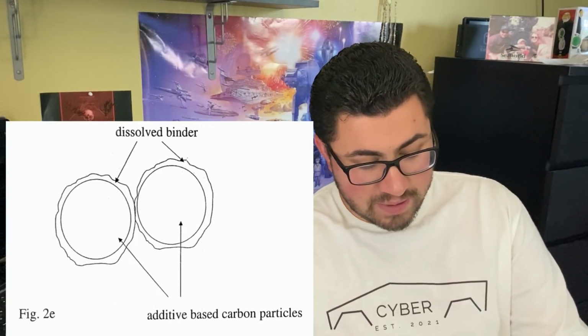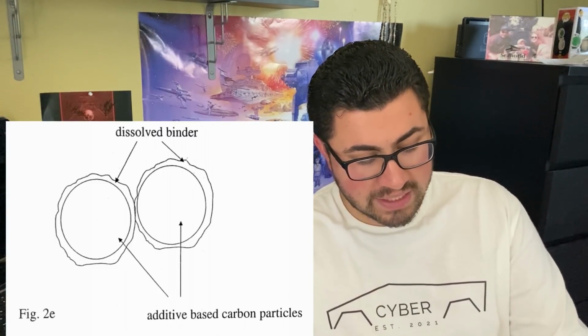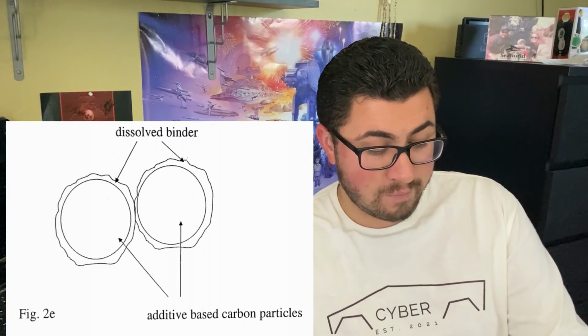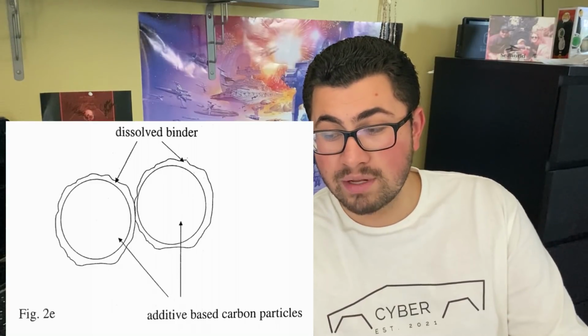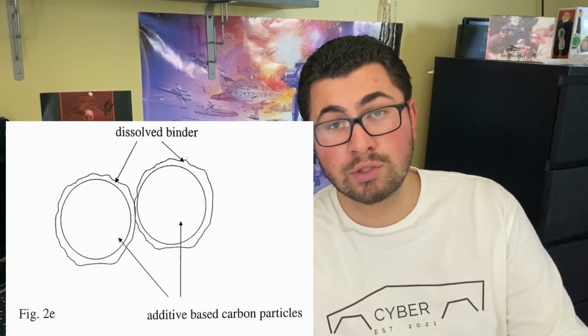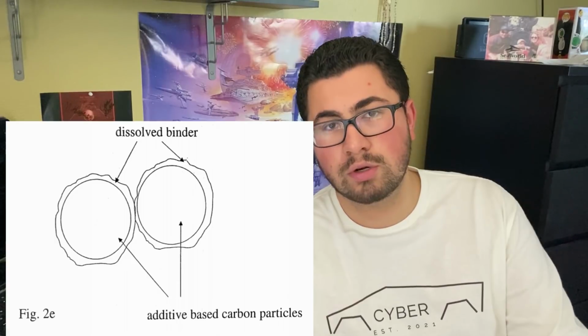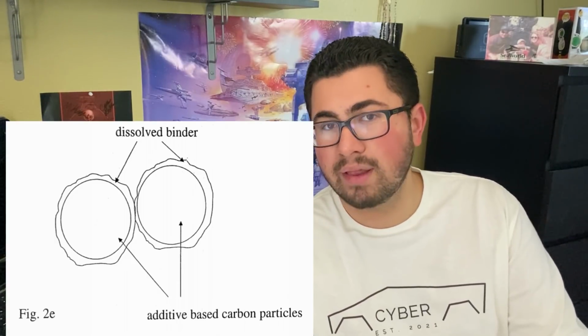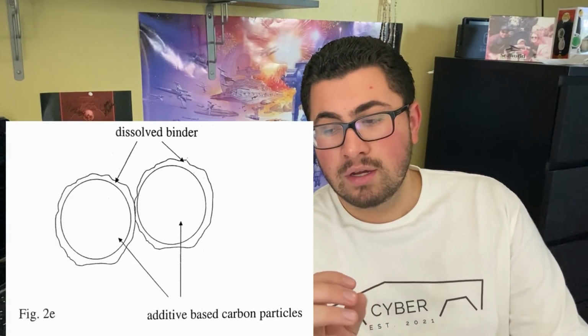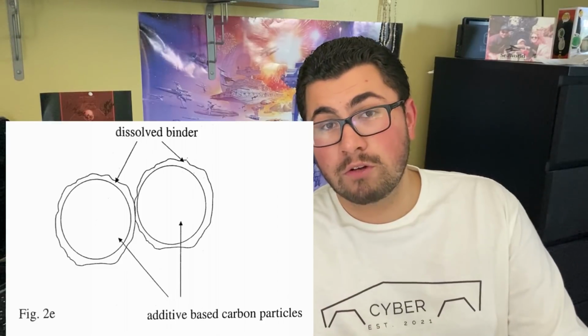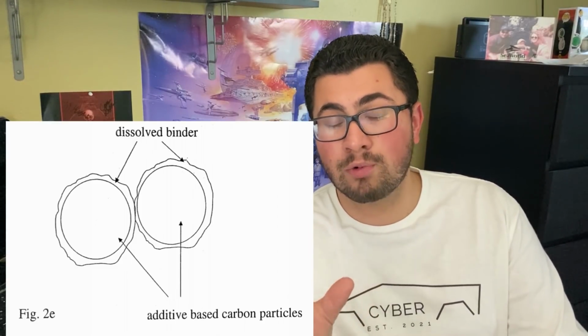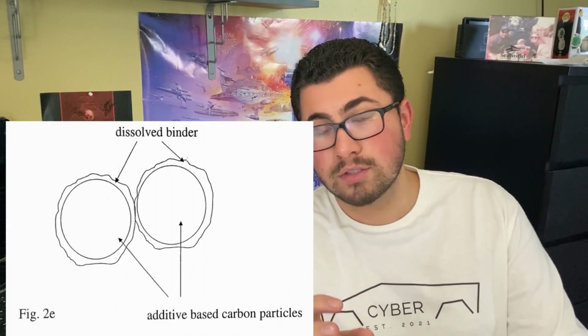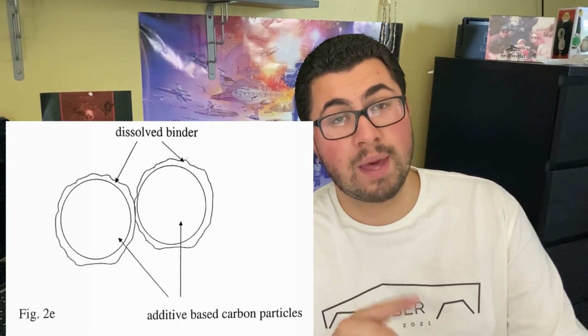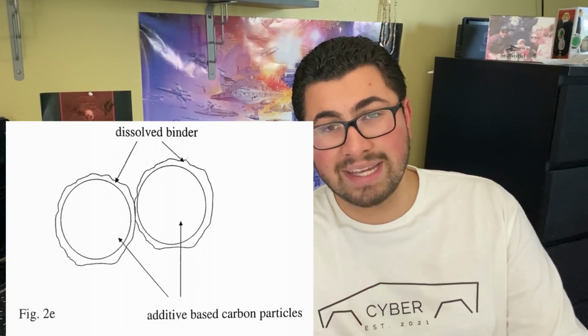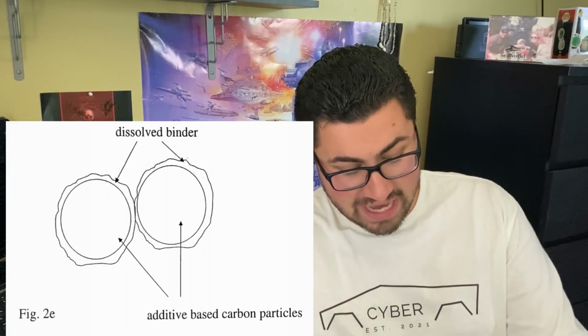Now this is additive-based carbon particles, and what you can see all around it is the dissolved binder. So what happens is when you add a slurry to the mixture, when you turn it into a slurry, because of what's called capillary action, the binder that's dissolved will actually completely wrap around the electrode material. So as you can see, it's completely circled around that material. And then when you dry it, it hardens and binds everything together.